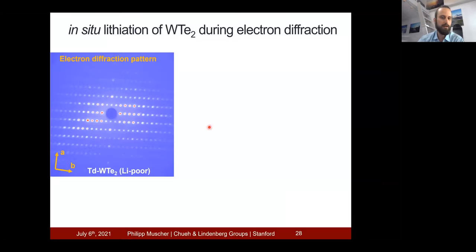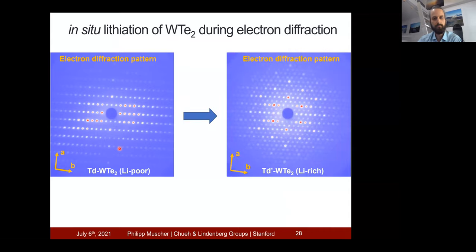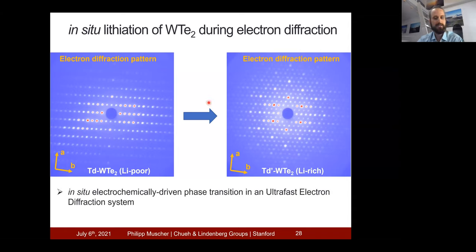First of all, this is the static diffraction pattern we find in this ultrafast electron diffraction system for tungsten ditelluride prior to lithium insertion. After lithium insertion, which we are doing in situ while electrons are hitting the material, we can see that the diffraction pattern is fully transformed, which corresponds to the new Td prime phase. This in situ electrochemically driven phase transition is the first time such electrochemistry has been shown to work in an ultrafast electron diffraction system. However, these are static diffraction patterns.